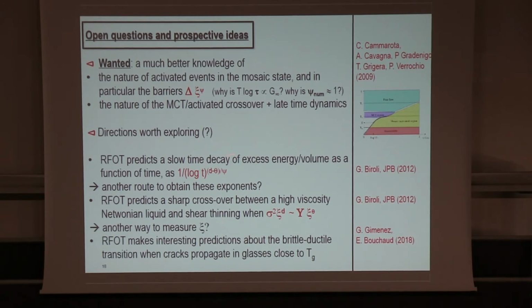So what are the open questions and some prospective ideas? I think what's really wanted is a much better knowledge of the nature of activated events in the mosaic state, and in particular, what these barriers, Δ ~ ℓ^ψ, are. Psi numerically seems to be around 1, which is small and not really compatible with simple bounds one could come up with. And there's also this mystery that the shoving model is exploiting a lot, and all these people thinking that RFOT is not really relevant, is that the product of the log of the relaxation time times the temperature seems to be, well, nearly proportional to the high frequency shear modulus. And that's something that's not completely natural in RFOT, but maybe Peter will have comments on that.